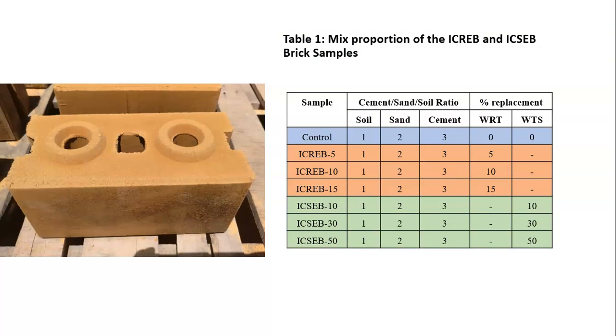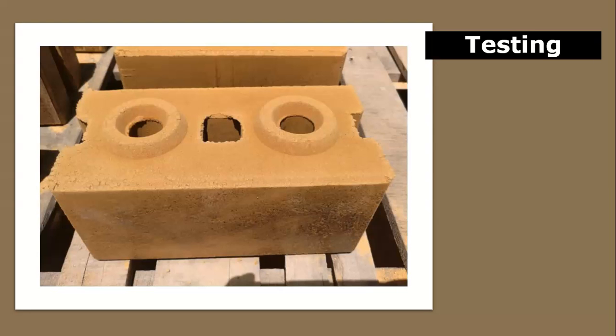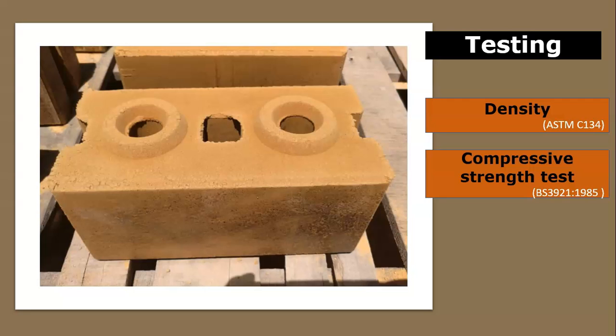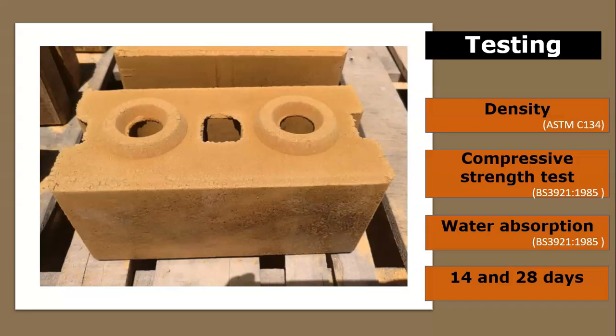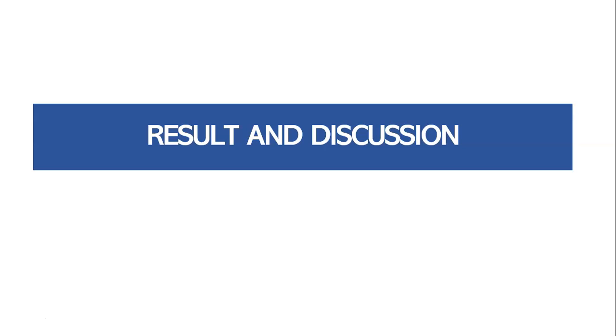The mix proportions of the ICREB and ICSEB bricks are shown in Table 1. And there are 3 types of testing conducted in this study. The density test was conducted based on ASTM C134. Meanwhile, the compressive strength test and water absorption test were conducted based on BS 3921 1985. All ICEB bricks were cured for 28 days and tested at the age of 14 and 28 days of curing. Okay, next is the results and discussion.